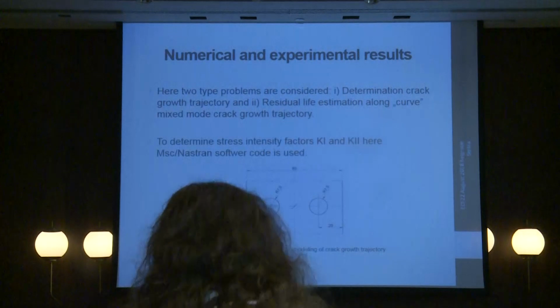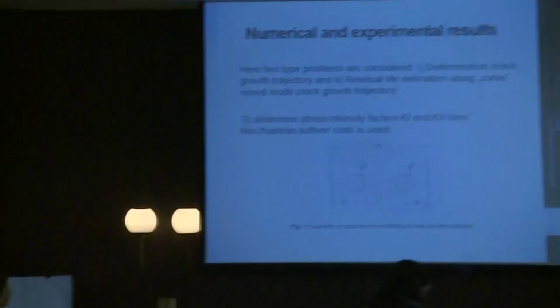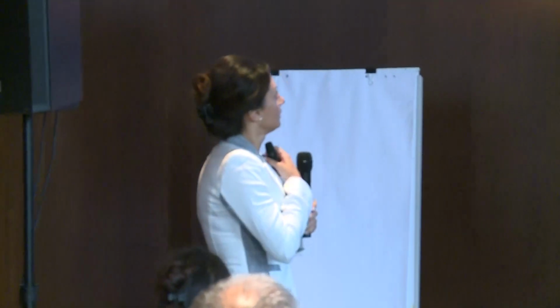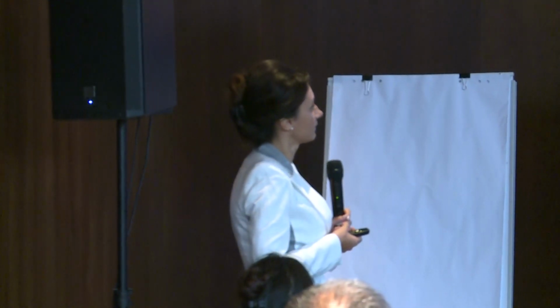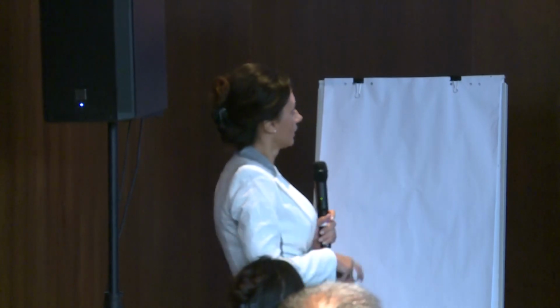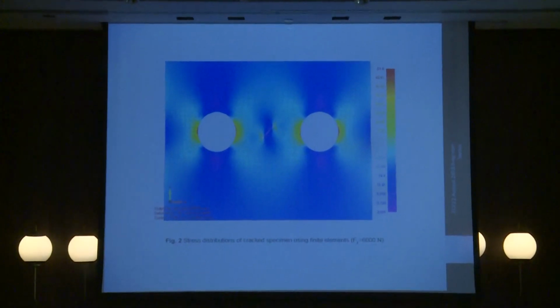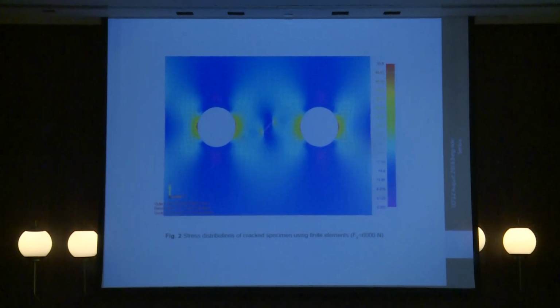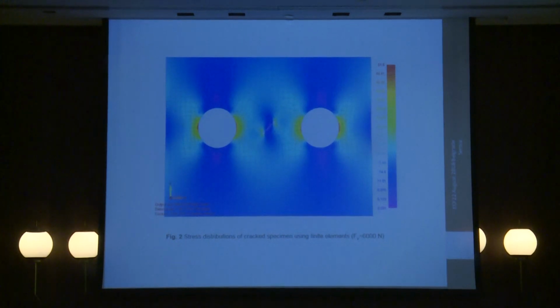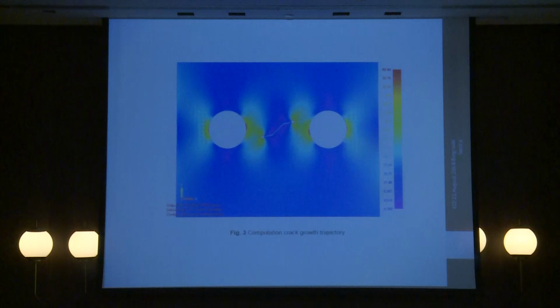Here on this slide we can see the geometry of the specimen for modeling of crack growth trajectory with the initial crack. Like I already mentioned, here we have two types of problems: determination of crack growth trajectory and residual life estimation along the curve. To determine the stress intensity factor, we use the Nastran software package. This is how the stress distribution of the cracked specimen looks in Nastran using finite elements. For this purpose, we use a load of 600 newtons, and the computation of crack growth trajectory for each new increment of crack length. You can see the stress distribution of the specimen and at the end of the crack.